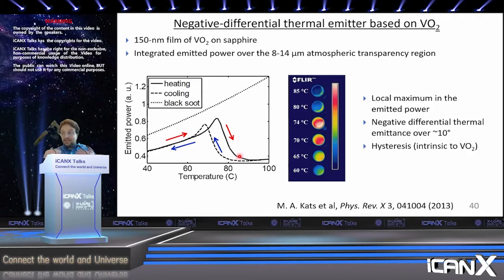Normally you expect thermal emitters, or any objects, as you heat them up, to emit more and more light. And here, as you heat it up, it emits less and less light over this region where you have this phase transition. And of course you also have a hysteresis associated with it, because there is a hysteresis that's intrinsic to the phase transition of VO2. And this is quite a striking result.